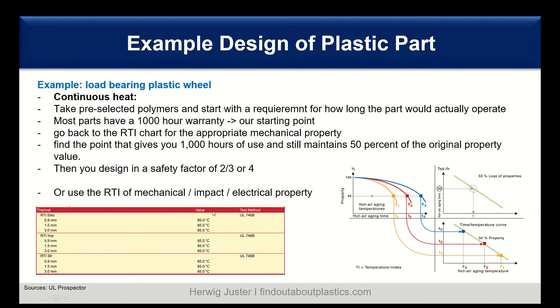In this case, regardless of whether we look at strength at different thicknesses, impact at different thicknesses, or electrical, it is always 85°C. So in this example — it is a polyamide — we know that can be critical. We need to check whether we fulfill the 1,000-hour requirement; however, the 100,000-hour rating is set at 85°C. So it really depends on the lifetime requirement. The faster way to examine this is via the yellow card.